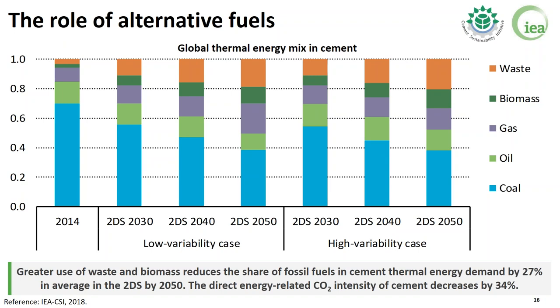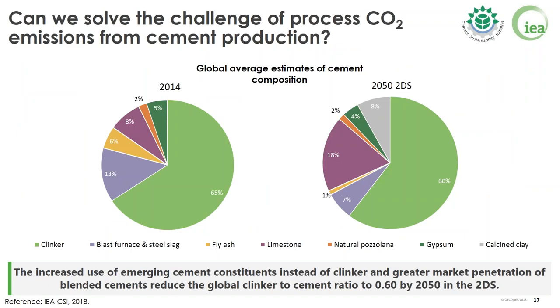Yes, thank you, Araceli. So I will proceed with the next slide showing one of the other levers that will provide the main contribution on the long term on CO2 reduction, and that is indeed the reduction of clinker content in cement. We have seen that in 2014, as an average, the clinker content in cement was 65%, and to comply with the 2-degree scenario at least cost, this share is supposed to decrease to 60% at global level, with of course some regional differences.